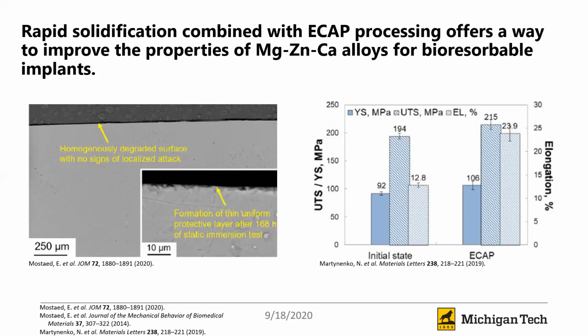And then ECAP processing greatly improves the ductility of the magnesium alloys, as well as improving the mechanical strength through allowing the alloy to dynamically recrystallize during processing, which eliminates the presence of very big precipitates by essentially crushing them up into smaller granules, as well as reducing the grain size, which reduces the amount of stress in the microstructure.